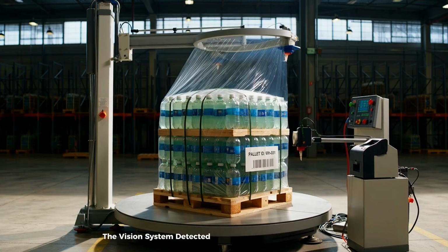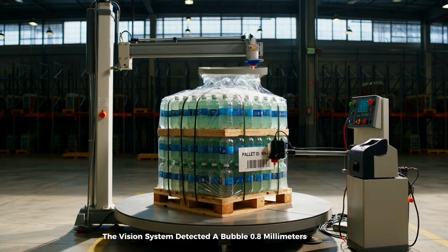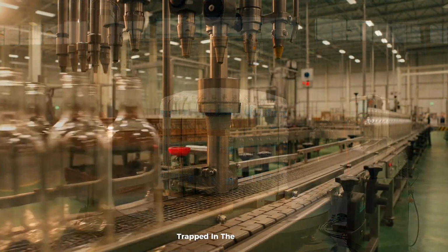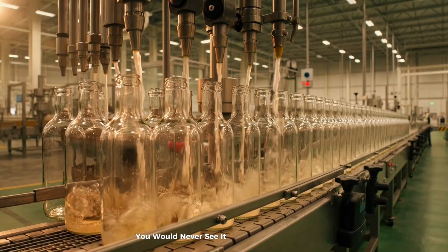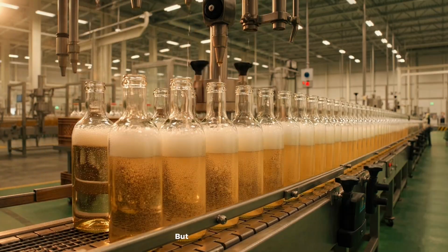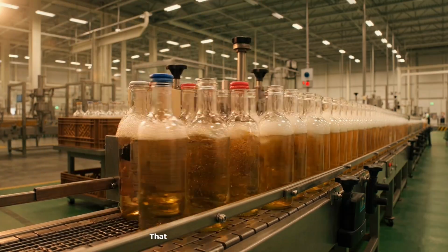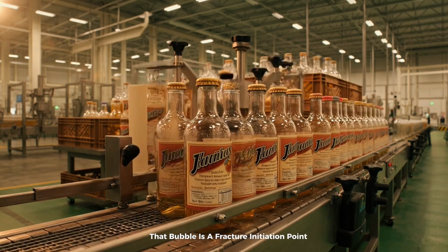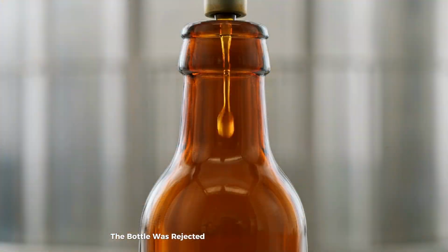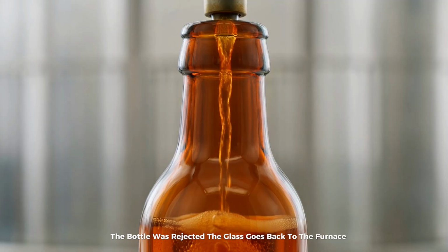The vision system detected a bubble 0.8 millimeters in diameter trapped in the bottle wall. You would never see it. You would never feel it. But under internal pressure, that bubble is a fracture initiation point. The bottle was rejected. The glass goes back to the furnace.